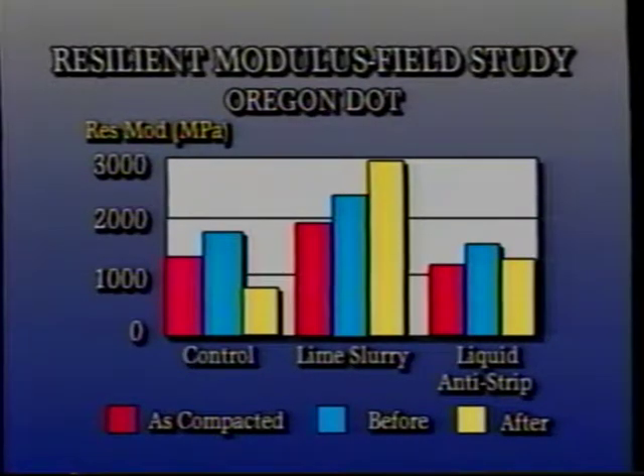The slurry is closely controlled. You can put the percentage in you want all the time, and it's continuous feed. The advantage of using the hot lime slurry is that it improves the water sensitivity of the mixes, but more importantly, it improves the high early strength characteristics of the mixes when compared with mixes with no lime. And this is important in that it allows one to extend the construction season, particularly in cold climates. As you can see from this chart, the index of retained modulus is improved substantially with the addition of lime to the cold-in-place recycling, demonstrating a tremendous improvement in water resistance or resistance to stripping. Furthermore, the chart also indicates that there is a higher early strength with cold-in-place recycled mixes when compared with similar mixes without lime.